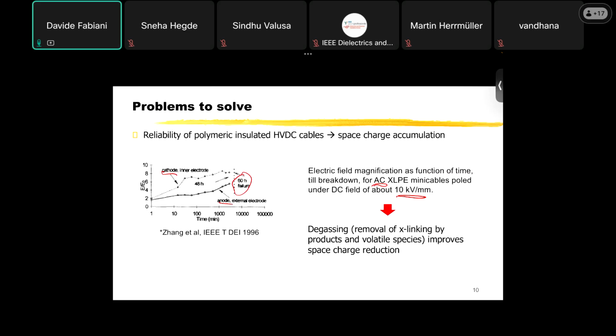So the idea was to use an AC insulation for DC. You have to remove all the cross-linking byproducts and volatile products. In that case, you can reduce space charge accumulation. You can reduce the increase of the electric field, and you can improve the reliability of the cable. So this was the idea that pushed the cable companies, at the end of the 90s, to use polymeric insulation for HVDC. But remember that the electric field was still quite low. The design electric field was below 10 kilovolt per millimeter.